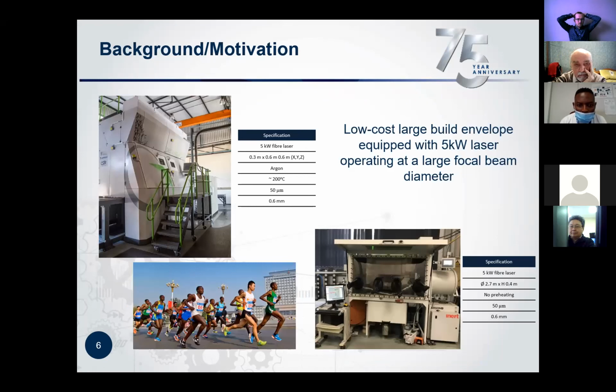For us at the CSIR, for quite some time we've been working towards building this large envelope machine, which is called the AeroSwift. It's a long project. From the initial design and testing phases it has been running for almost over a decade now. The system is equipped with a 5 kilowatt fiber laser. The build envelope is 0.3 meter by 0.6 by 0.6 meter. We use argon as a shielding gas during the build. The preheating system, yes, we can preheat up to 600, but we're quite comfortable at 200.